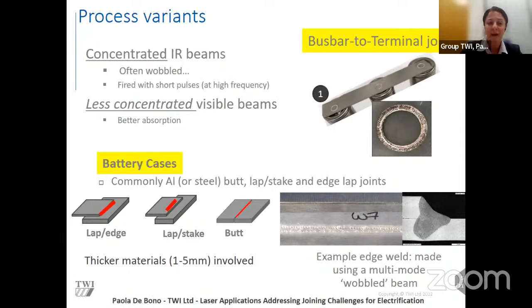Obviously we come across the green laser. Also Christian earlier was giving an interesting presentation about dynamic beam laser. There are obviously the ring mode laser beams. So there is a range of options available trying to address some of the joining challenges for EV application. And also we shouldn't forget about the battery cases. Typical materials are aluminum and steel, with different joint configurations and thickness ranges that vary from 1 to 5 millimeters, and in this case partially penetrated joints need to be achieved, and the use of a wobbling technique has helped, for example, to overcome some porosity challenges that are typically encountered for this type of joint.